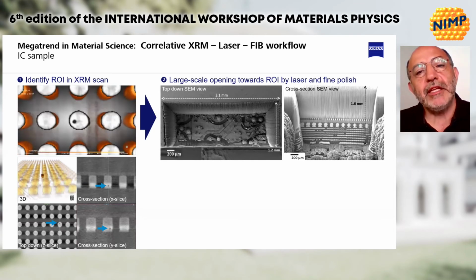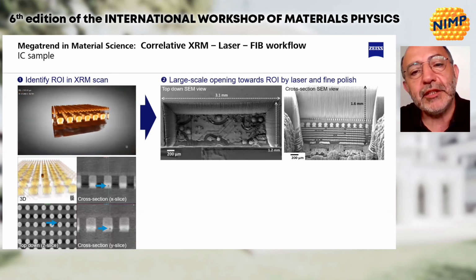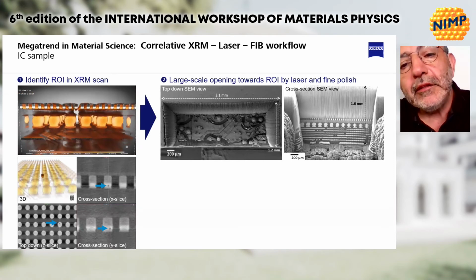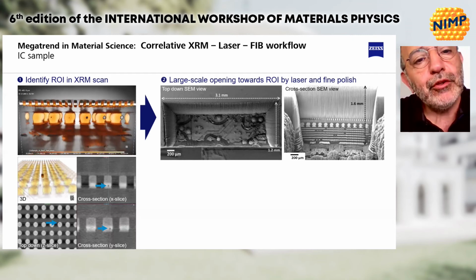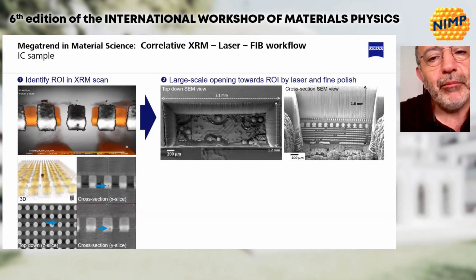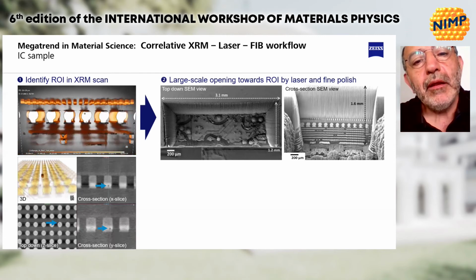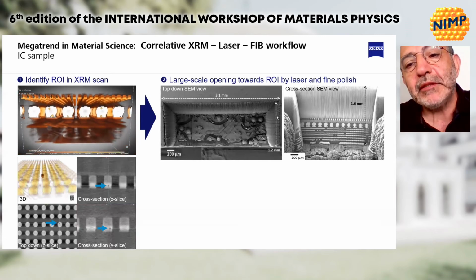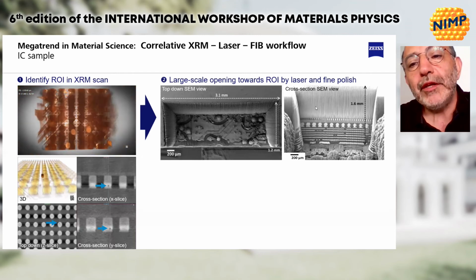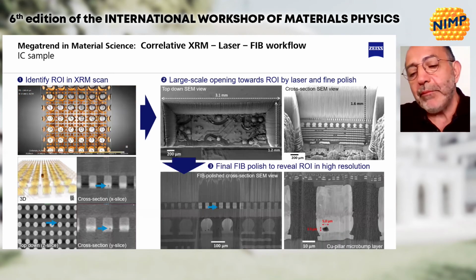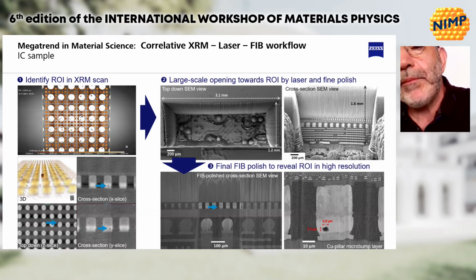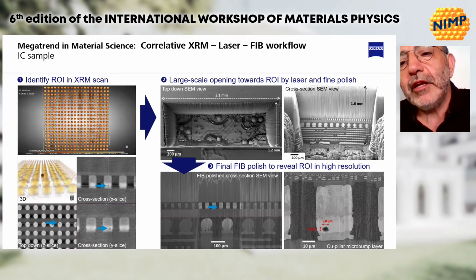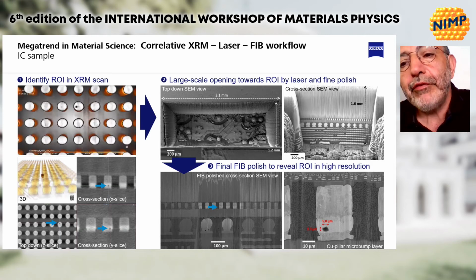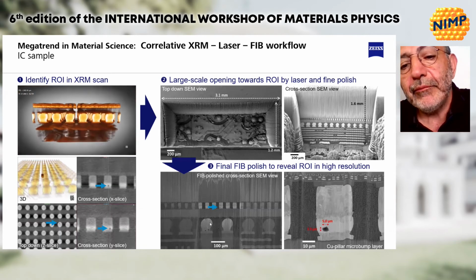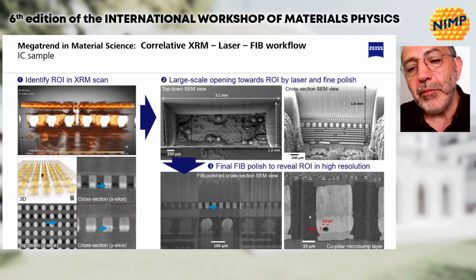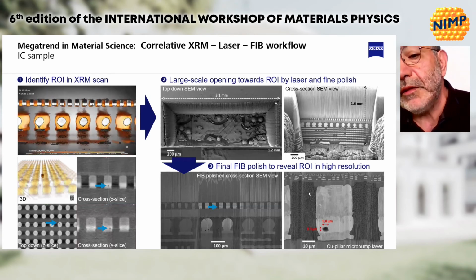The most important part here is that the coordinate system in 3D from the laser is correlated with the coordinate system from the synchrotron images, or in this case from the X-ray microscope. Once you really make a deep cut, you can see here the scale bars in the millimeter range, then you move to the next modality, which is the cross beam using the gallium FIB, just to polish the area of interest, and then finally to perform the images that you are aiming to analyze with nanometer resolution.